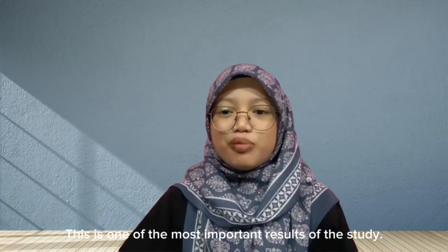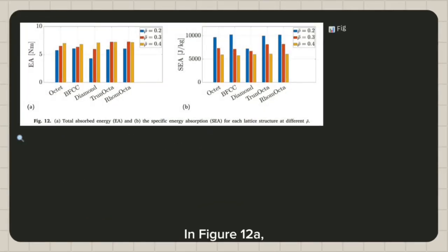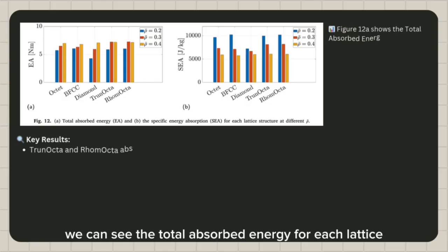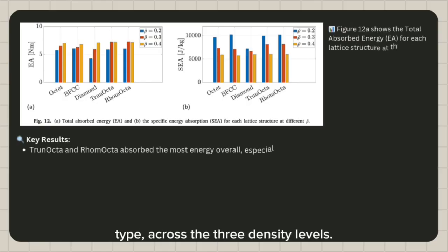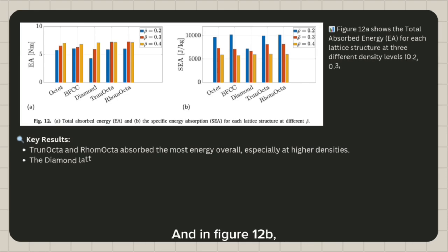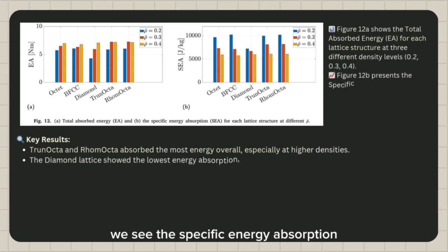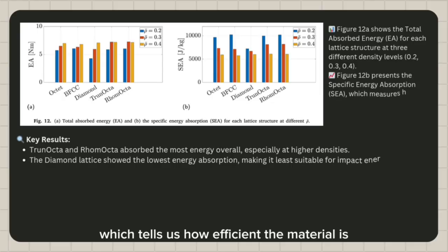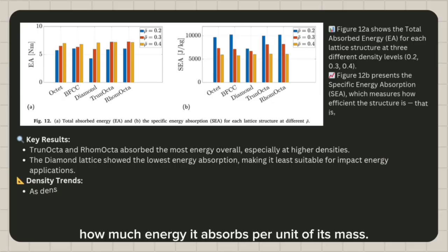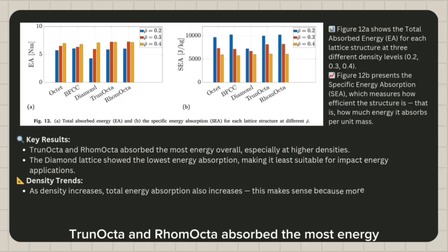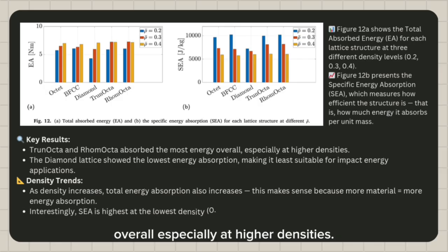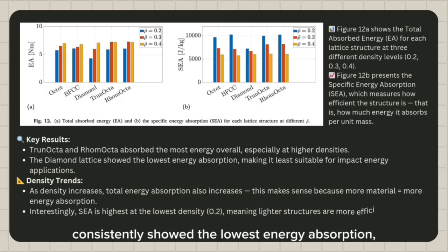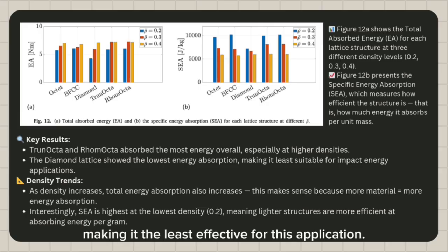This is one of the most important results of the study. In figure 12a, we can see the total absorbed energy for each lattice type across the 3 density levels. And in figure 12b, we see the specific energy absorption, which tells us how efficient the material is, basically how much energy it absorbs per unit of its mass. The results are clear. TrunOcta and RhomOcta absorbed the most energy overall, especially at higher densities. The diamond lattice consistently showed the lowest energy absorption, making it the least effective for this application.